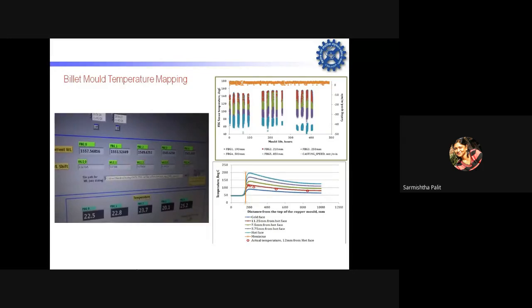So here is Industry 2.0 actually. You can take a call based on this live, real-time data, which has been captured throughout the life of the caster and verified through the model. The red dots are all experimental data at the depth where we have placed our sensor, and all others are from the mathematical model. This is the first time a billet mold model has been verified through experimental data by embedding fiber Bragg grating sensors on the mold, with data captured in real time throughout the life of the caster. We completed this work in 2016, and in another caster one experiment has already been completed. We are going for further experimentation and implementing this completely as an instrumented billet mold, which we hope may come up in the market in the coming few years.